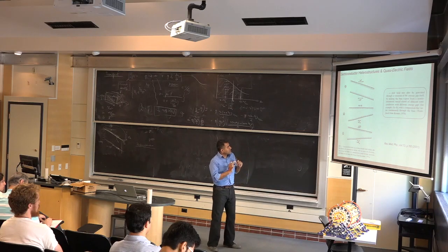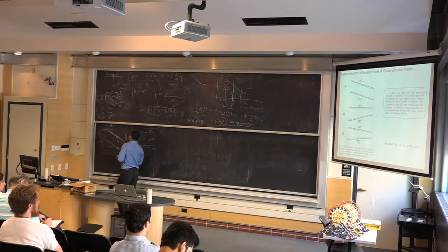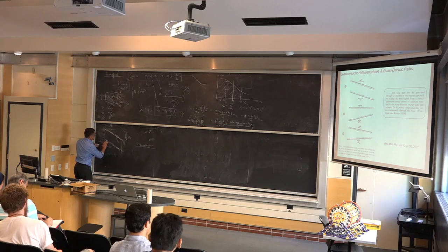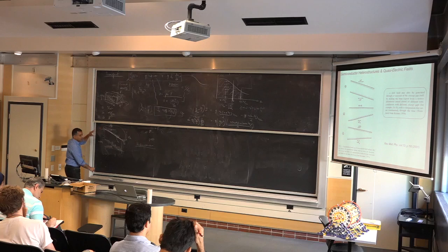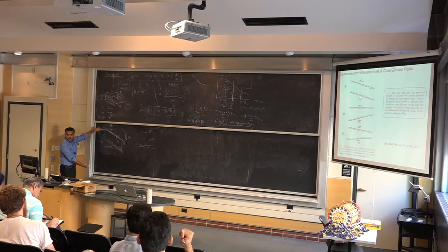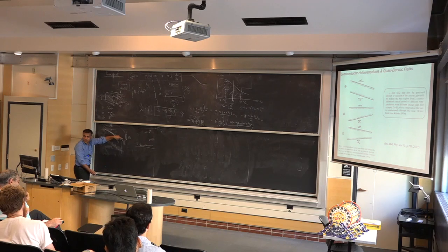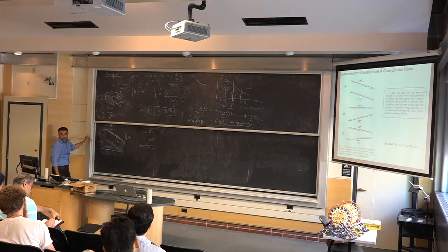But now you create a semiconductor, and this we can create when we do material growth and all that sort of thing. I create a semiconductor where on the left side, I have a very large band gap. But on the right side, I have a very small band gap. I create such a semiconductor. So my energy band diagram here would look something like that.